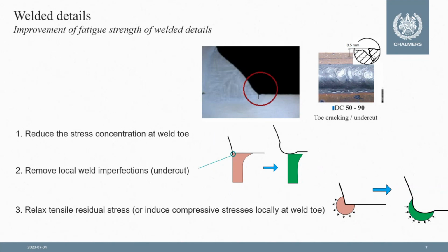The second action that one could take is removing possible undercut or other surface defects that exist in this location. And the third action refers to the presence of residual stresses, which often are high tensile residual stresses, that we can either relax or, if possible, introduce as compressive residual stresses. That would enable us to improve the fatigue strength of the detail with reference to cracking at this location. So these are, in principle, three different actions that one can think of with the objective to improve the fatigue strength of this kind of details.